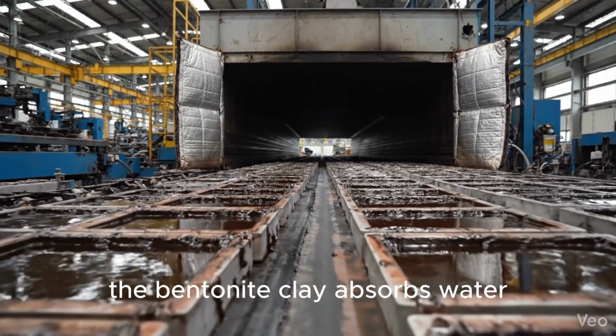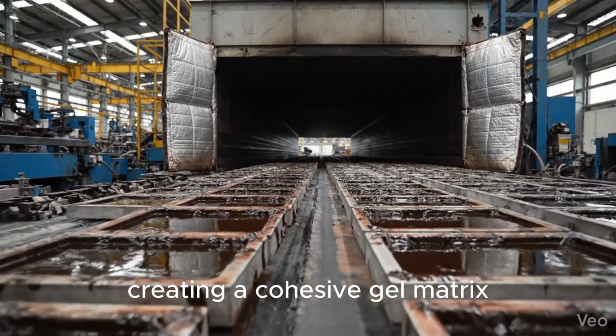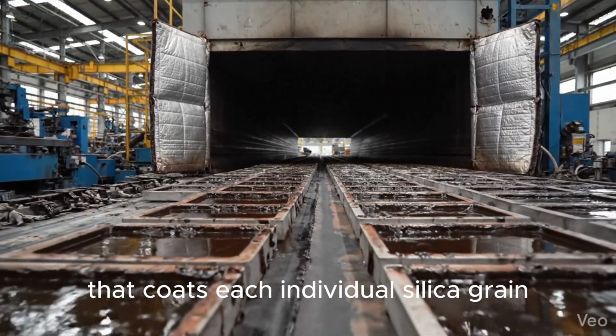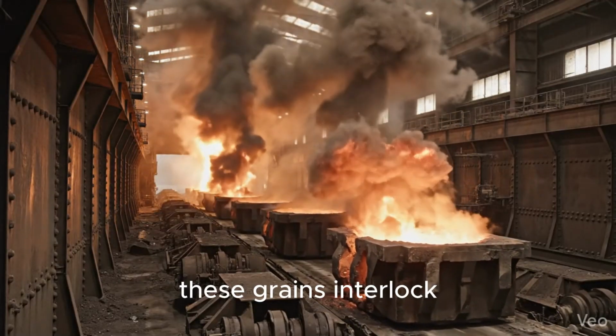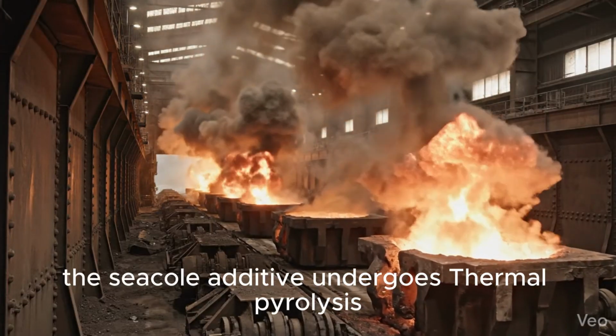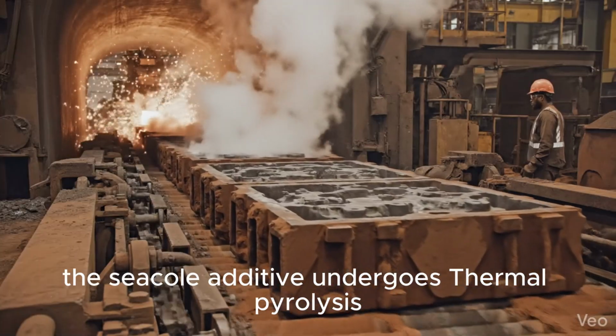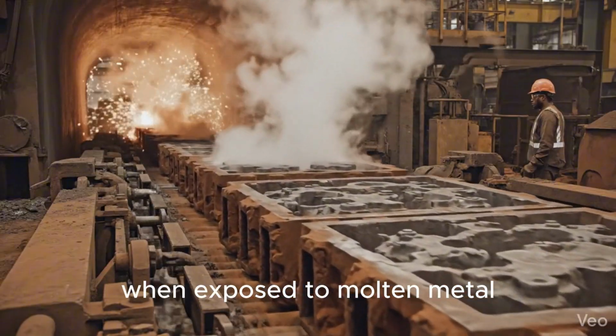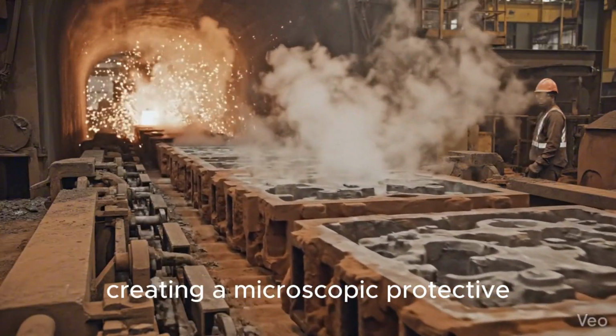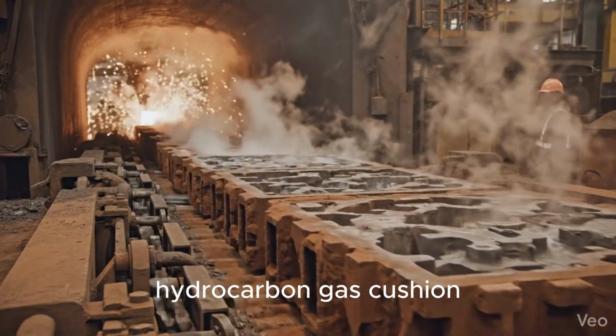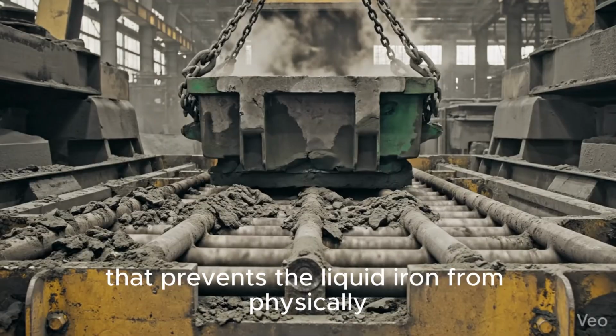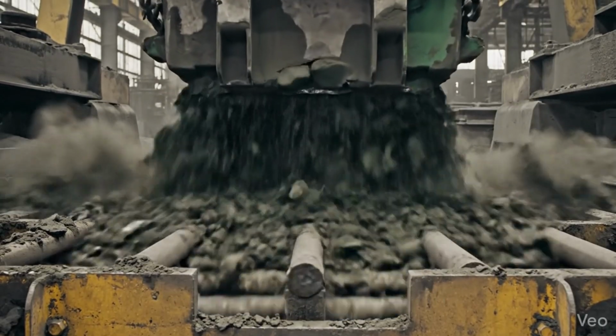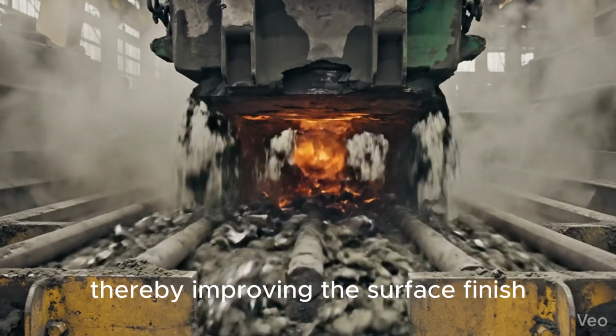The bentonite clay absorbs water, creating a cohesive gel matrix that coats each individual silica grain. Under mechanical compaction, these grains interlock, providing high compressive mold strength. The sea coal additive undergoes thermal pyrolysis when exposed to molten metal, creating a microscopic protective hydrocarbon gas cushion that prevents the liquid iron from physically fusing with the silica sand, thereby improving the surface finish.